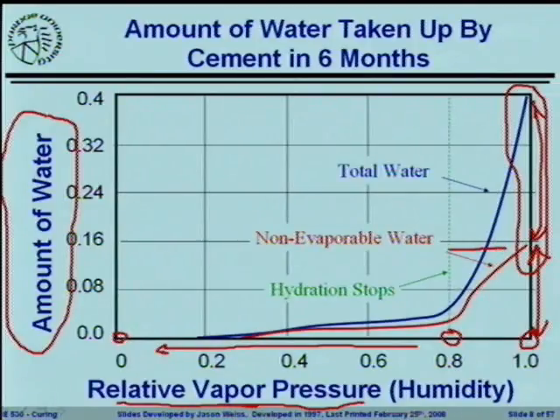As you drop the relative humidity, water is going to start leaving the system. As more and more water leaves the system, the cement is going to start hydrating less and less. And once you drop below about 75 or 80%, there is a marked decrease in how much of the reaction is taking place in this particular system. Once you get below about 40%, you just have layers of water inside of the overall pore structure, and that water is not going to react. It's just going to hang out on those surfaces. So really the crucial point, and what a lot of people use as a rule of thumb, below about 75%, 80% relative humidity, they assume the hydration reaction stops.